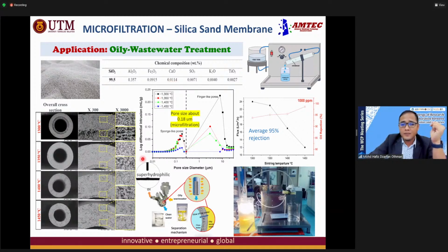We also measure the contact angle. It is super hydrophilic, meaning that the membrane surface has a very good affinity toward water, and it will repel most of the hydrophobic pollutants. This is very suitable for oily wastewater. In oily wastewater, the water, which is hydrophilic, is allowed to pass through the membrane, and we also have hydrophobic contaminants. With a super hydrophilic membrane surface, it will reject them, so we can produce very high quality water.